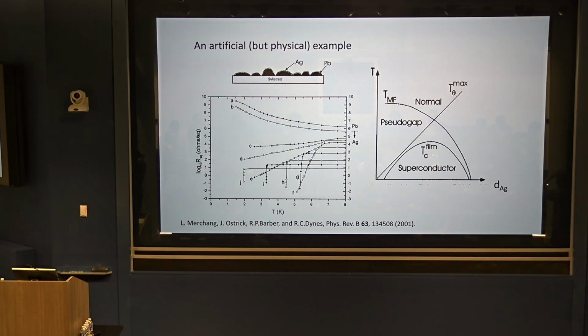About your first comment, the cuprates, I'm quite confident in the underdoped regime are in this regime where pairing is large and phase fluctuations govern TC. I'm less certain that the iron-based superconductors ever get into that regime. Oh, no. We can take inspiration crystallographically. It was very interesting to have 122s that, if you don't have this contrast and epitaxy, alloy, but if you have enough contrast and epitaxy, they form a true quaternary that has different layers. And that's what you're after. No, but I'm after, in cuprates, you might be able to find a similar recipe to get to that. Oh, okay, yeah. So that's the inspiration.